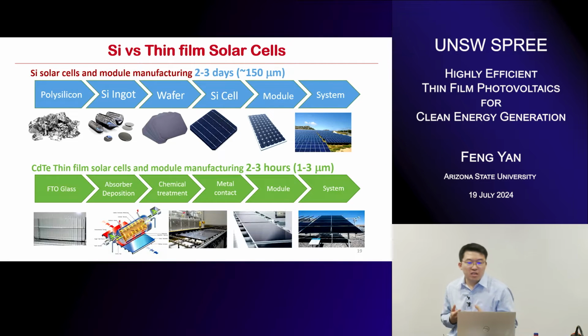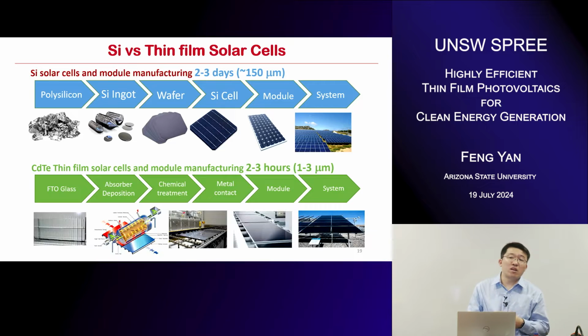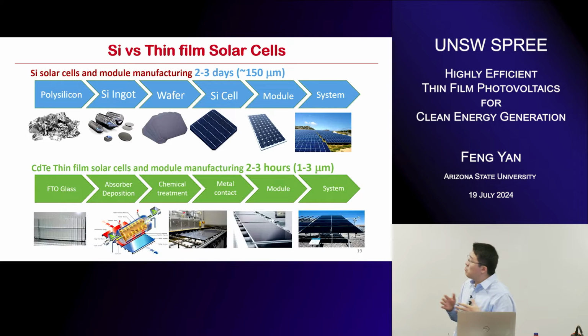Comparing silicon and thin film solar cells, we can notice that silicon even dominates the market now, at close to 80% or 85%, but its manufacturing cost and period are pretty long, spanning around 2 or 3 days, including the silicon ingot from the sand to the system. But here is an example of a cadmium telluride thin film solar cell. You will see that it can be manufactured within 3 hours. It's like printing newspapers, pretty fast and scalable.